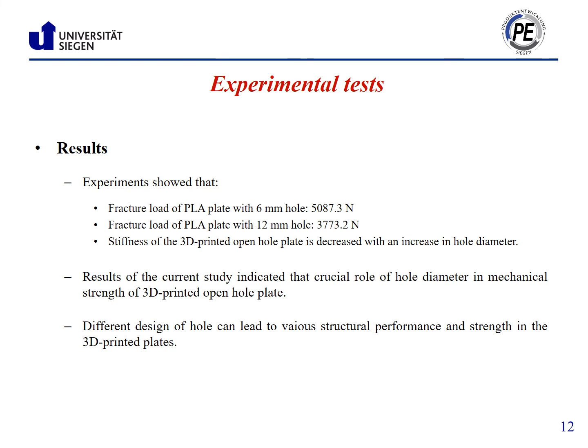Experiments showed that the fracture load of the PLA plate with 6 mm hole is around 5000 Newton, and it is reduced to about 3700 Newton for the specimen with 12 mm hole. In fact, these obtained results confirm that the stiffness of the 3D printed open hole plate is decreased with an increase in the hole diameter. Results of the current study indicated the crucial role of the hole diameter in mechanical strength of the 3D printed open hole plate.